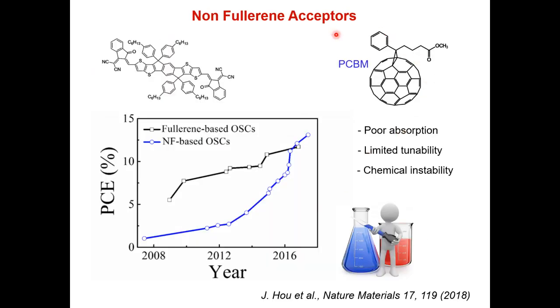Initially, all the devices were built with PCBM, fullerene derivatives, because they are very good acceptors. Their LUMO is very deep, so you can have very efficient dissociation of the excitation into charges. But the efficiency, which is the electrical power generated over the light power absorbed by the device, basically saturated around 10%, which was good, but not good enough to compete with silicon and other well-established technologies.